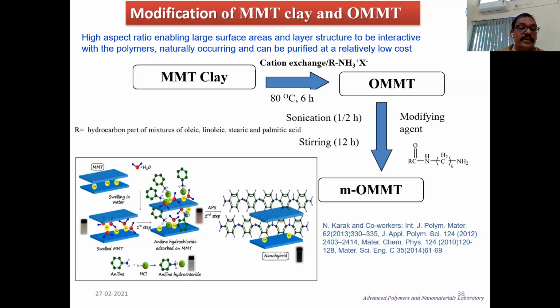We have also used a new strategy where this modification can be done in situ. We have used aniline hydrochloride as the exchanging cation, and there itself we polymerize using oxidative polymerization technique with the nano clay, and we got a hybrid system with polyaniline and nano clay, which subsequently was incorporated in this hyperbranched bio-based polymer, and we have seen a lot of improvement that I shall discuss later.